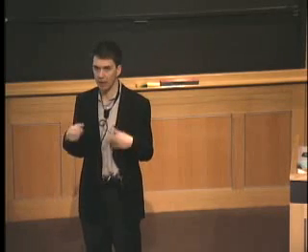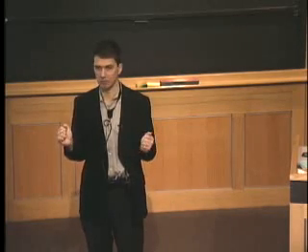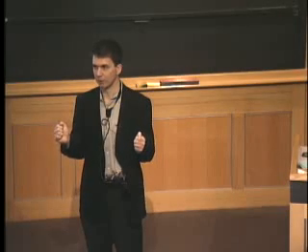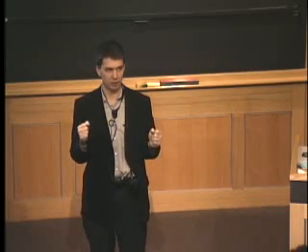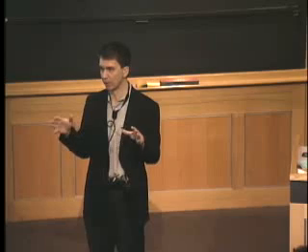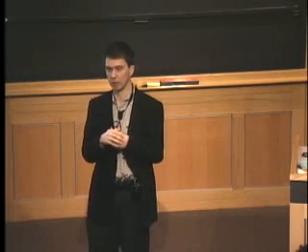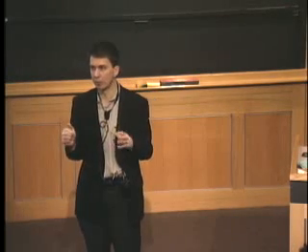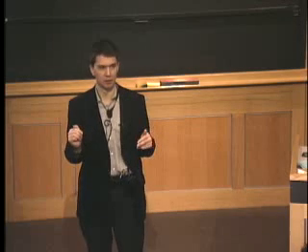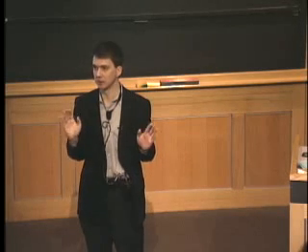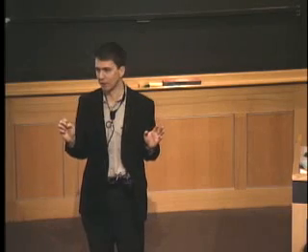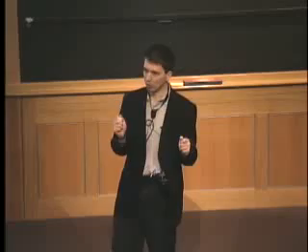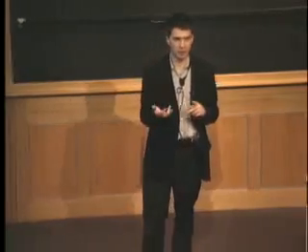And the reason is you've taken away a degree of freedom of the system. If you actually then calculate a defect, the system wants to polarize, but you haven't given it the option because you haven't included it in your model. So I would say be aware of people who show you equations of state. Everybody can fit an equation of state. Any potential that has more than one fitting parameter can fit an equation of state. It's the low symmetry details, surface energies, defects, that are hard to reproduce.